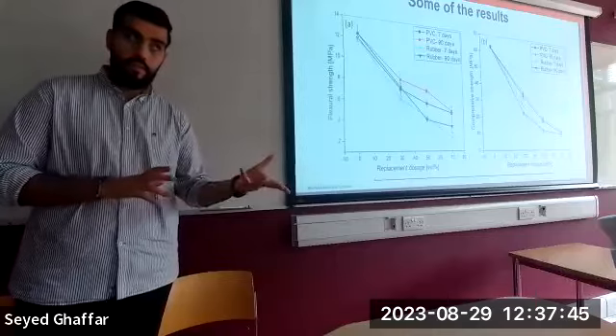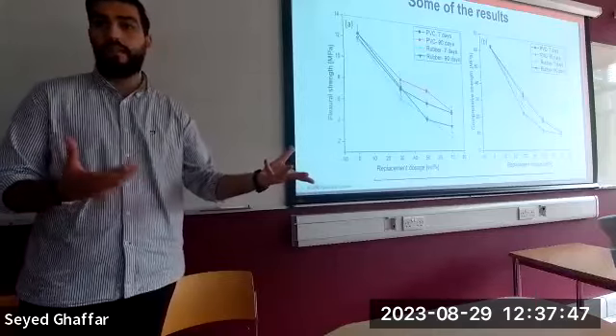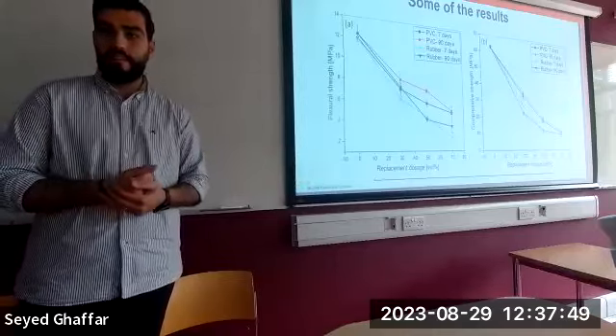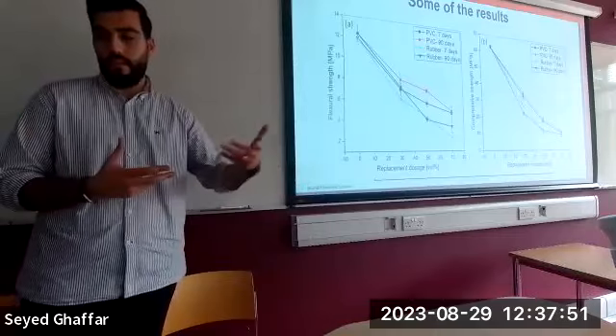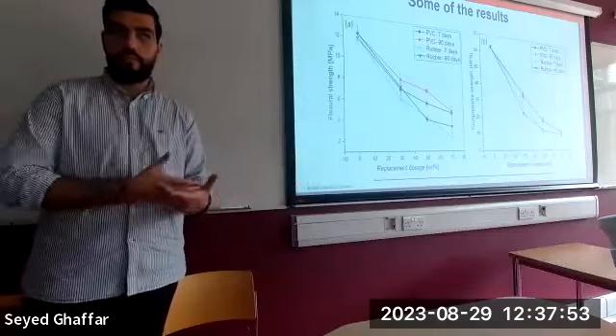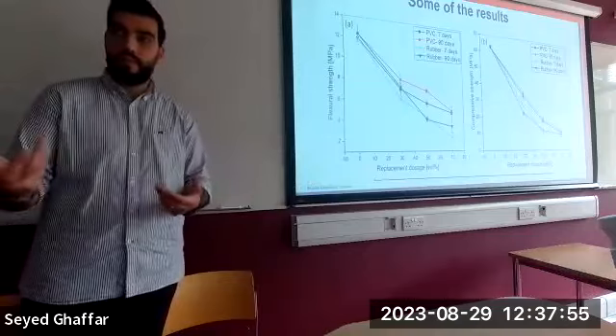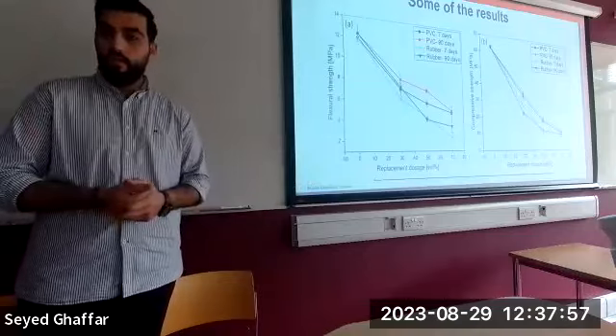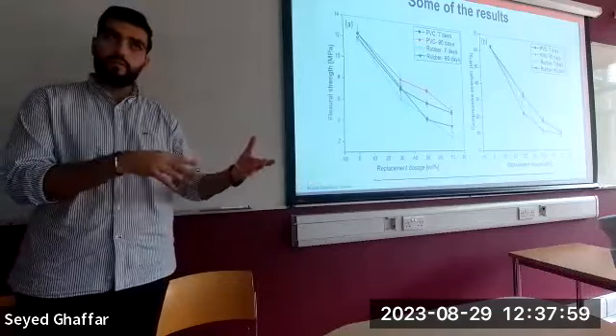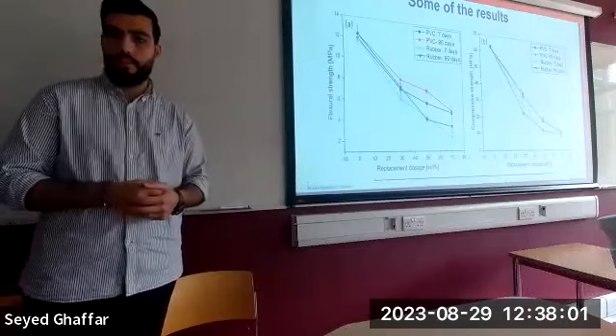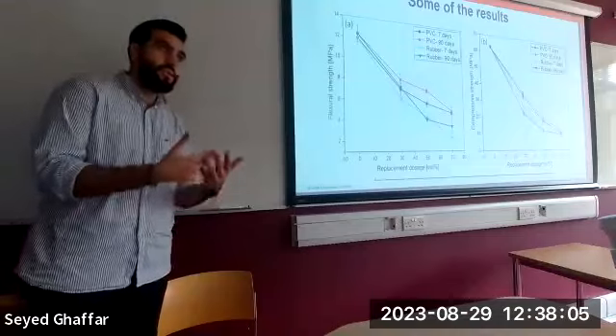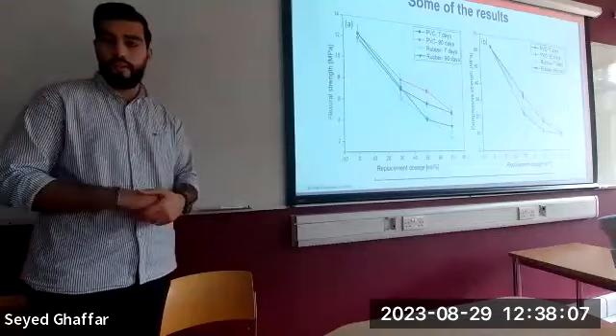So it's 70% recycled aggregates and 30% is sand. Instead of having 100% sand and gaining very high compressive strength, for example, we can have only 30% sand and get a very moderate compressive strength, use it for non-structural load bearing applications. So by no means are we saying that we have developed a structural load bearing product.